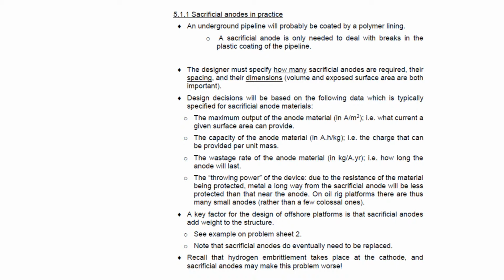One final thing to remember as a comment is that when sacrificial anodes are used, they do cause the surface potential of your two-metal system to change, and the surface potential probably changes to a value where the hydrogen evolution current in most situations will be much faster than it was without the sacrificial anodes.